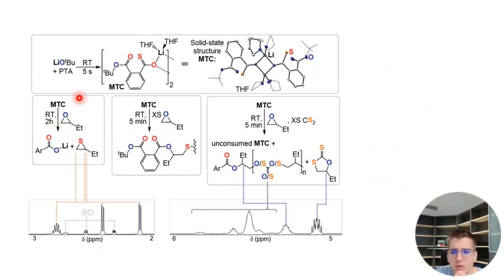And so we had good reason to believe at the time already that the slowest step of the reaction was after the chain end inserted the cyclic thioanhydride to form this lithium dithiocarbonate. And the insertion of the epoxide by such a species was likely the slowest step of the polymerization. This was relatively clear because the copolymerization of CS2 and epoxide was much faster than the copolymerization of PTA, the cyclic thioanhydride, and epoxide. So from that it was relatively clear that likely the insertion of the epoxide is the slowest step. So I went to study such an intermediate synthetically.